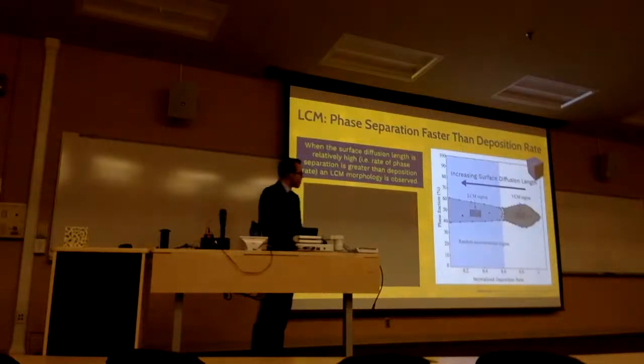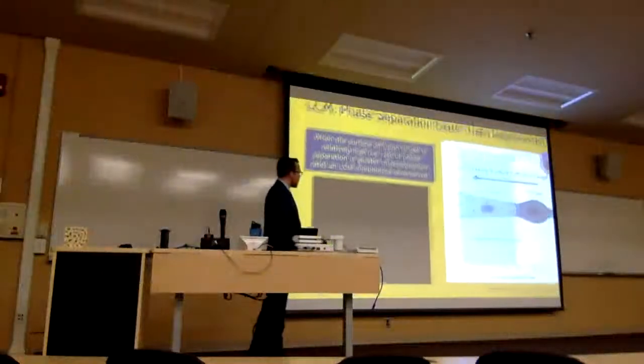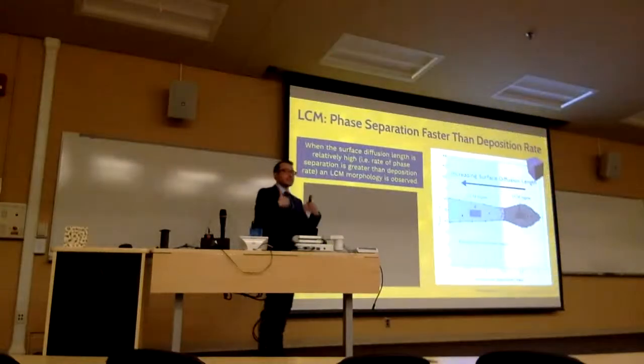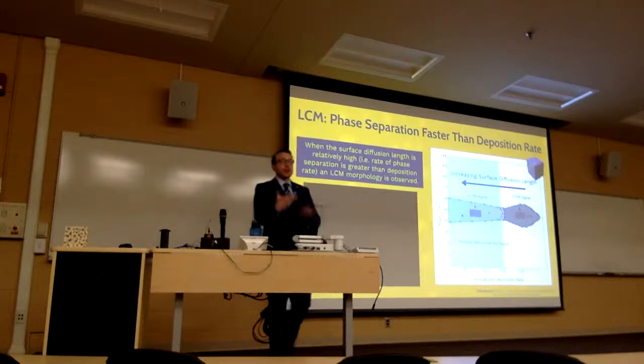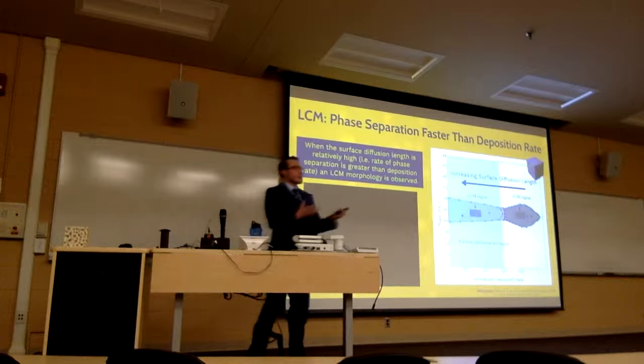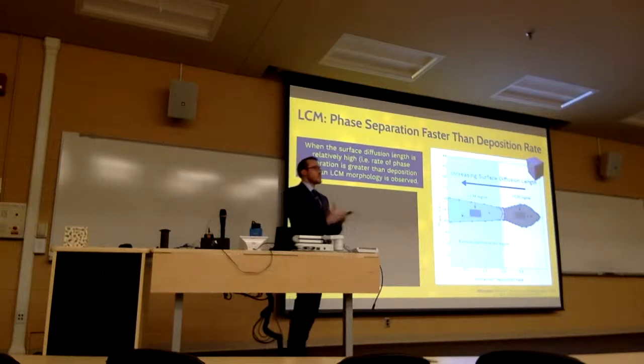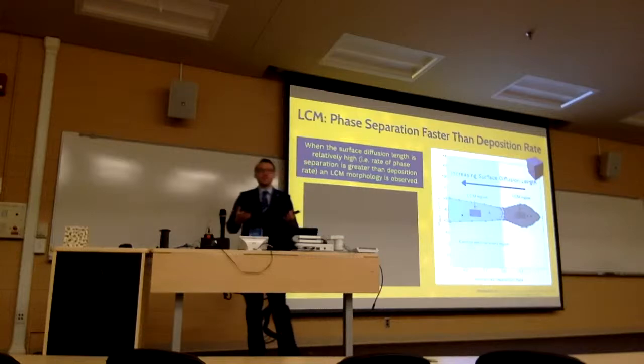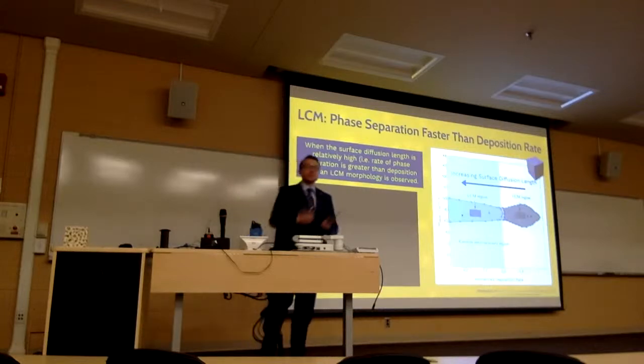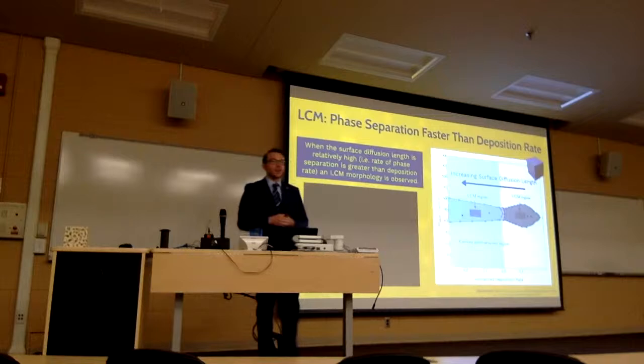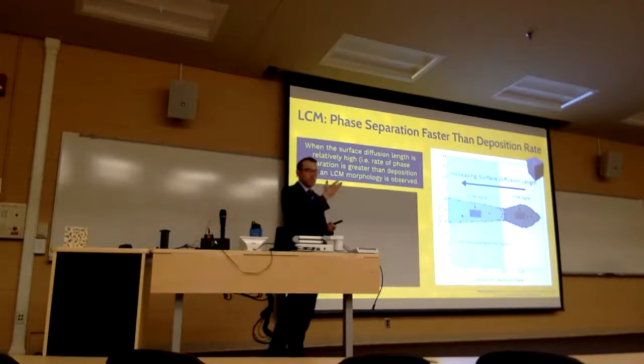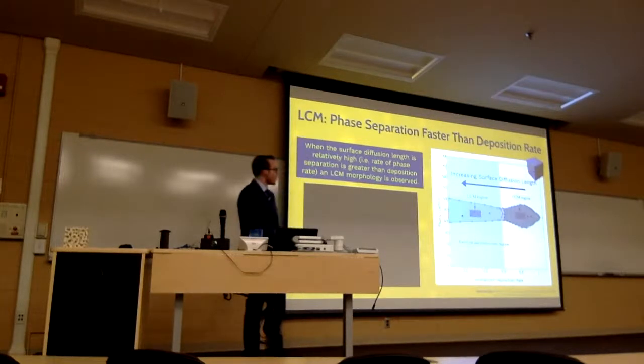And I wish I could show you the video, of course it's not working, but what you would see in the video is, as the sample is being deposited, an equal amount of yellow and blue atoms deposit onto the substrate. They have enough time to diffuse and to phase separate before the next layer arrives. And the next layer that arrives, like atoms, have a simple job of just finding regions of like phase underneath, and they build up into this LCM-like morphology you can see schematically in this corner.